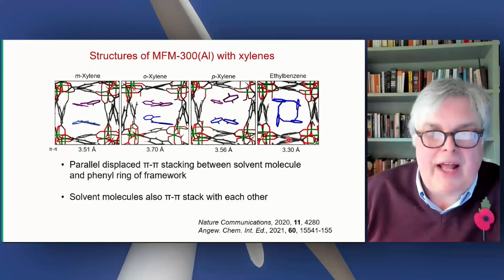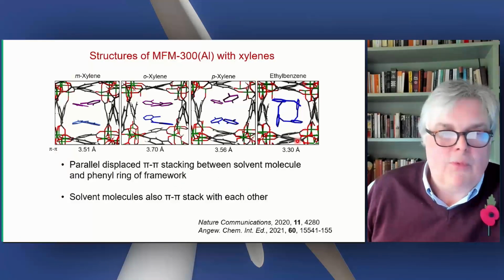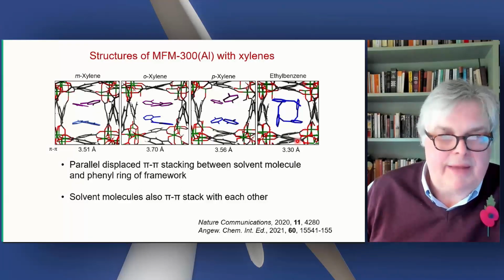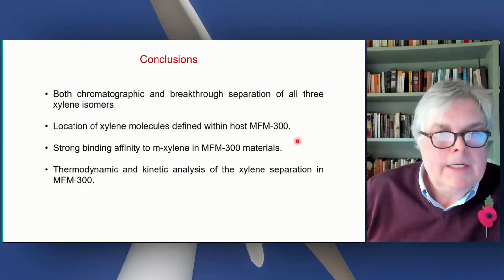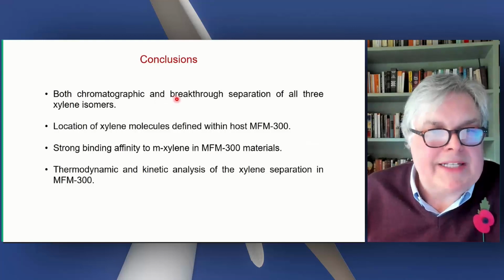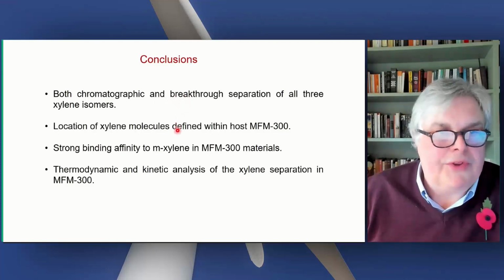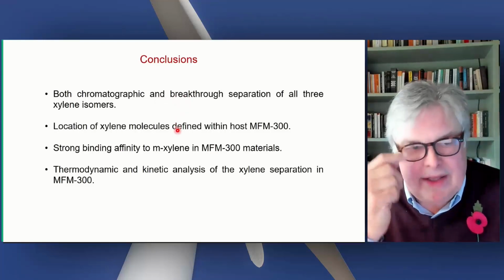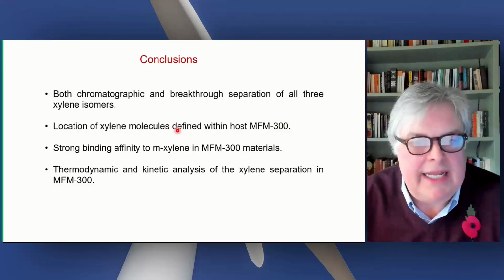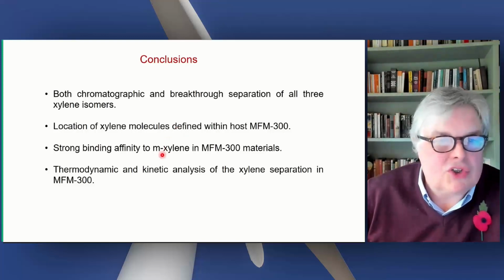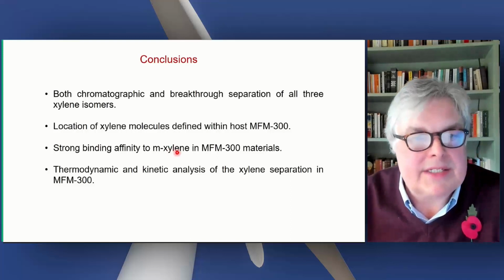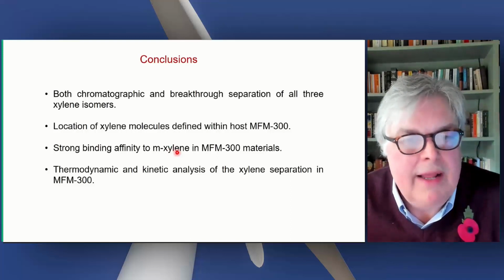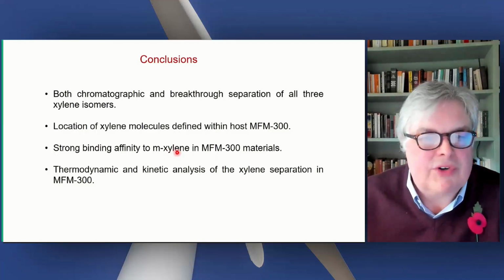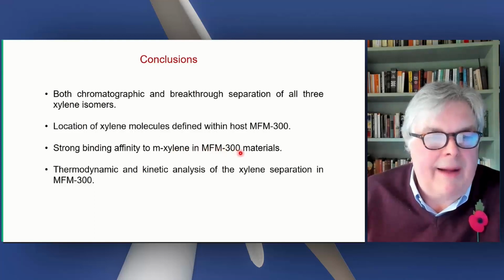And you can see here ethyl benzene packs in a rather different way, and therefore does show a different type of selectivity. So we see both chromatographic and breakthrough separation of all 3 xylenes. We see that we can find the location of these xylenes within the host. We see strong affinity to metaxylene. I didn't go through that structurally, but metaxylene seems to interact very strongly with our MOFs.